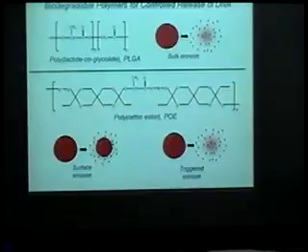Whereas this new polymer that we've been working on in collaboration with other people doesn't degrade in bulk; it's a surface erosion. In this case, the polymer really resembles a bar of soap, where only the surface, which is in contact with the solvent, gets degraded and falls apart, whereas the interior of the polymer microsphere remains intact. By doing so, there will not be any acidic degradation product accumulation, so the DNA conformation will be maintained throughout the entire process. And also, by manipulating the chemistry of this polymer, one can incorporate different triggering molecules so that you can modulate these processes, the degradation, by changing the environment.